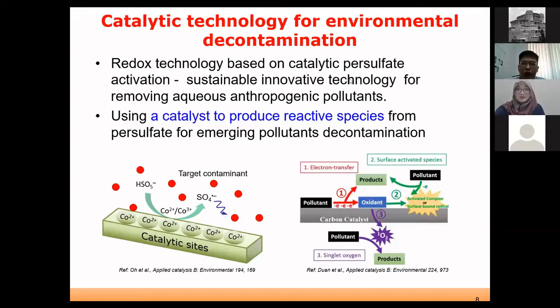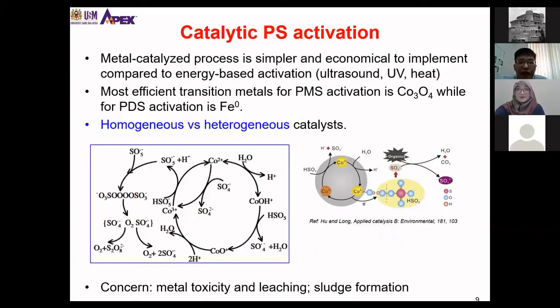So for this catalytic persulfate activation, a lot of people are using metal-based catalysts. Right? So metal-based catalysts, in fact, are simpler and more economical compared to other ways of activating persulfate. So persulfate, you can activate it using other approaches, for example, ultrasound, UV, heat, and so on. But of course, the preferred way is metal-based catalyst. Right? The catalyst, by definition, is supposed to be reusable for 100 cycles, 200 cycles, and 300 cycles. Okay? So that's why it's simpler and more economical. Whereas if you use energy-based activation, you have to continuously supply energy. That means the process is not very sustainable.